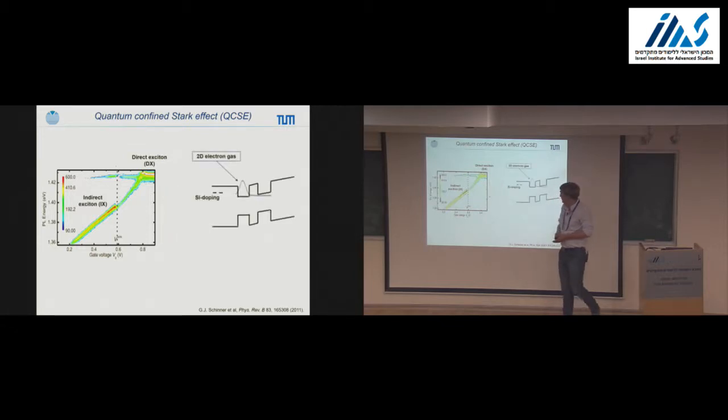If we have flat band, the situation is such that the indium gallium arsenide quantum wells have a lower band gap than the backgate, such that we have a doping from the silicon, and we end up having a 2D electron gas in the lower quantum well. And actually, when we excite our system now, we have excitons on there, plus these 2D electrons.